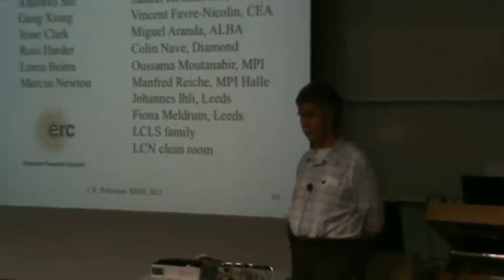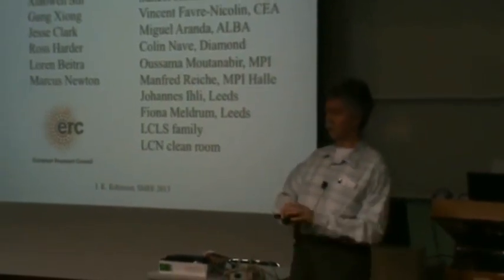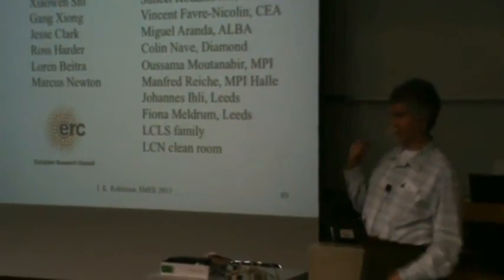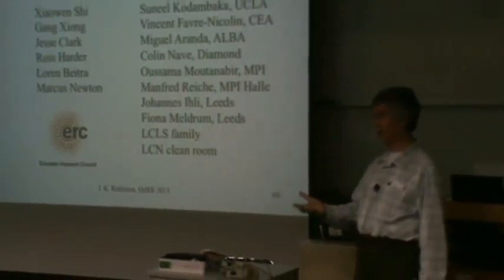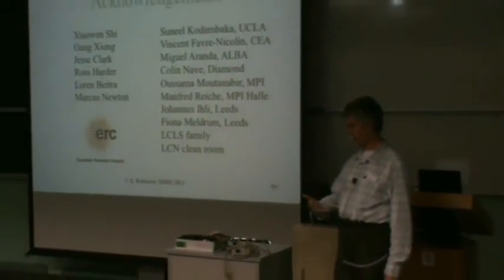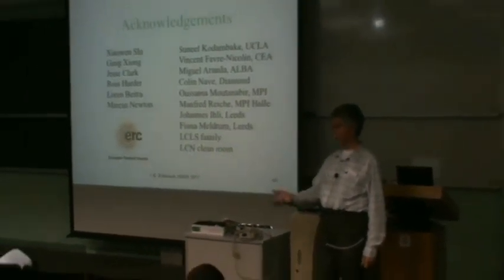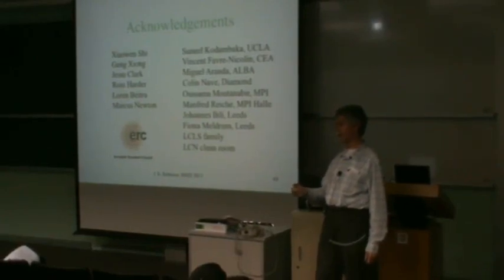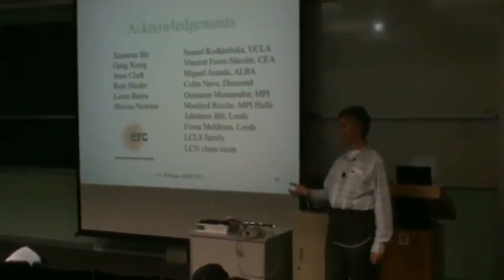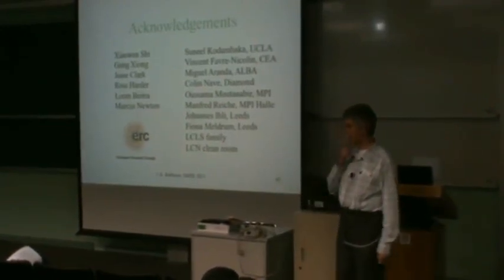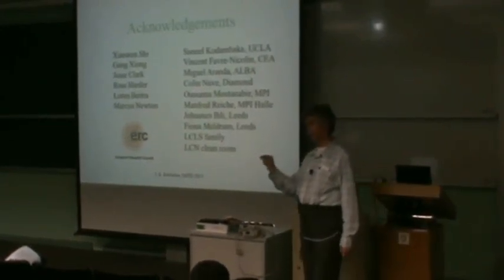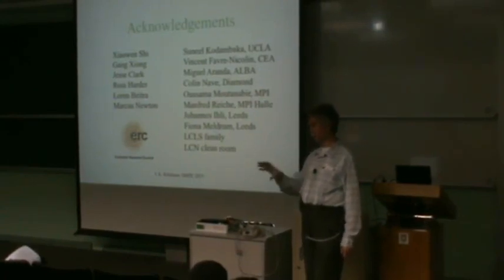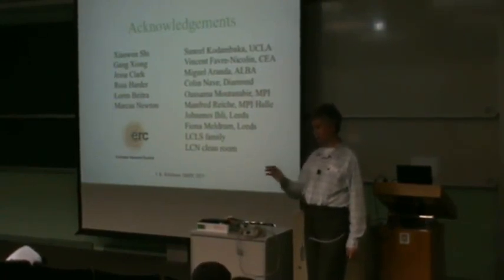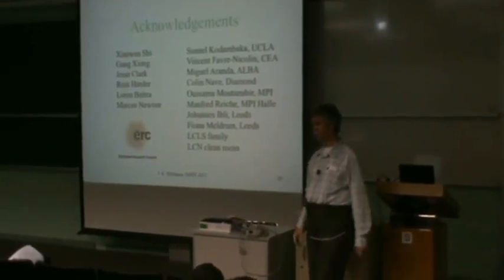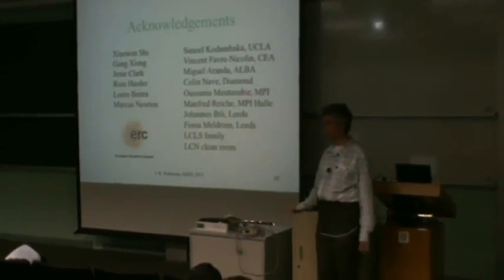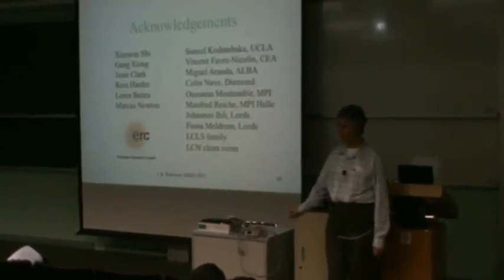How was it mounted? These were mounted on SiO2, so the gold was prepared. It's actually the method I mentioned with the patterning, where you can use a thin gold film and heat it in a furnace, and you get de-wetting into individual crystals, and you get millions of them, so you've got plenty to burn up. And then you just find a nice one that's pointing in the right direction, that's free from lots of neighbors, and once it's stable for 2 shots, it's probably stable for a few hours, but that was the experimental approach that we took.